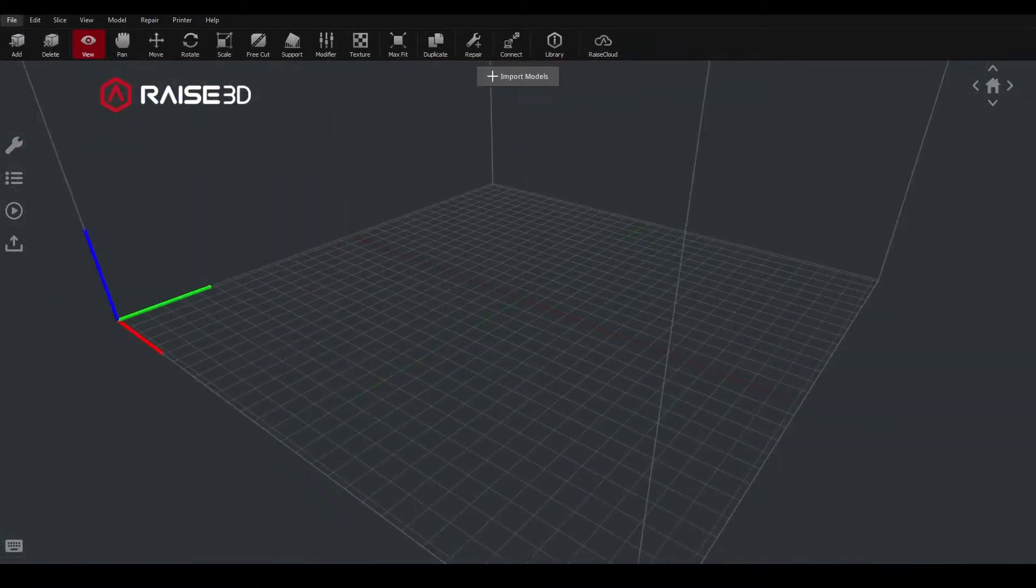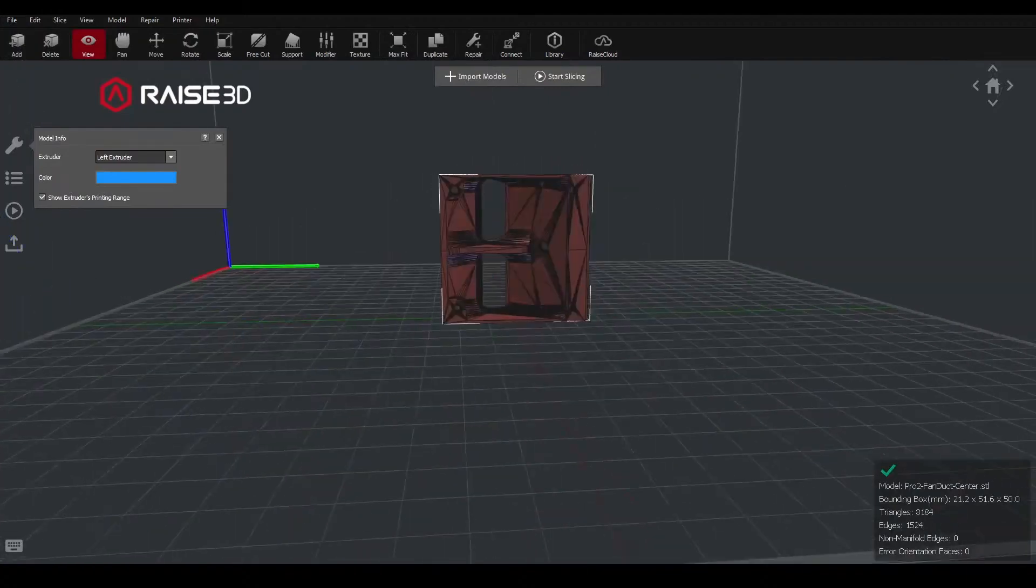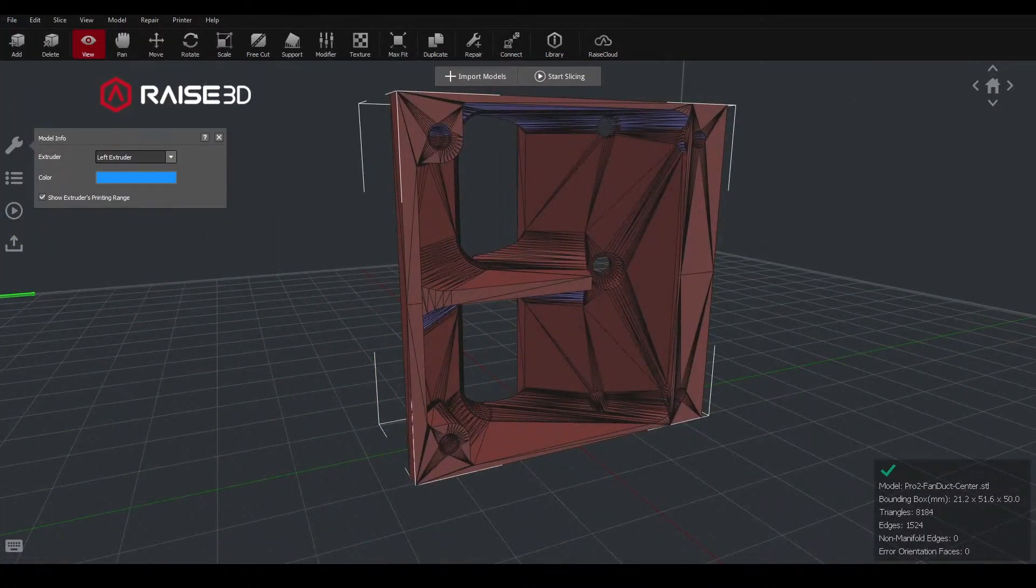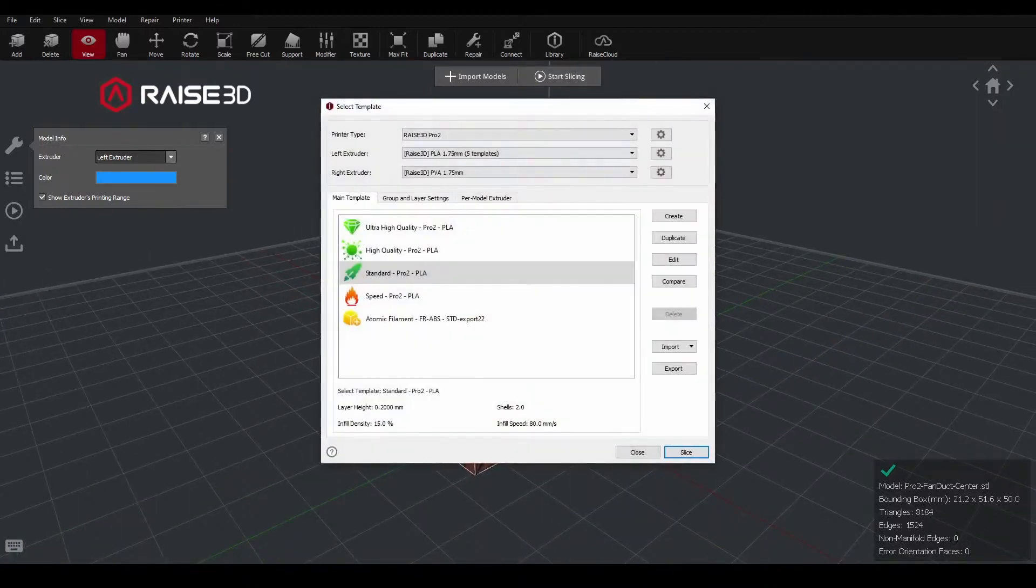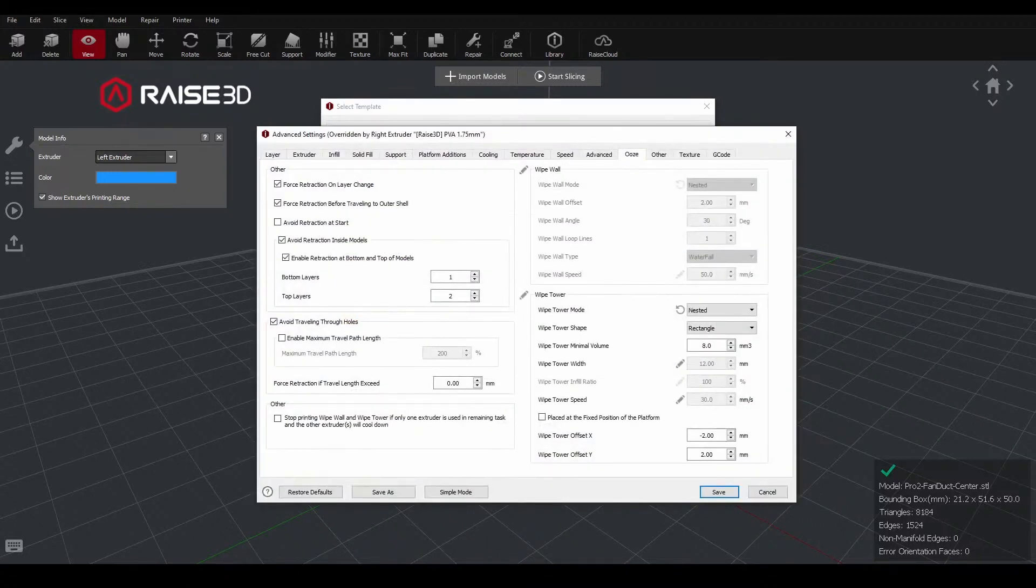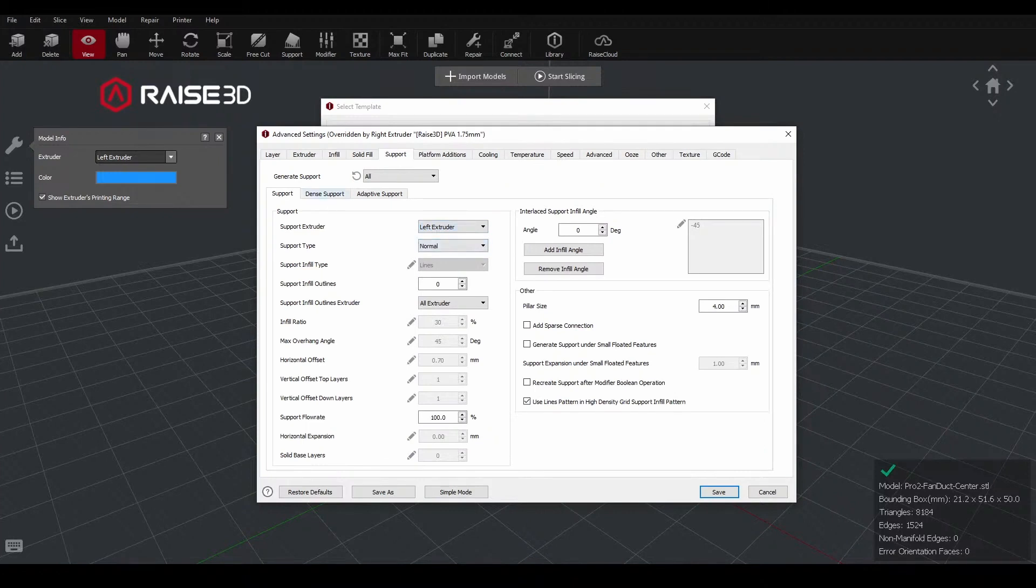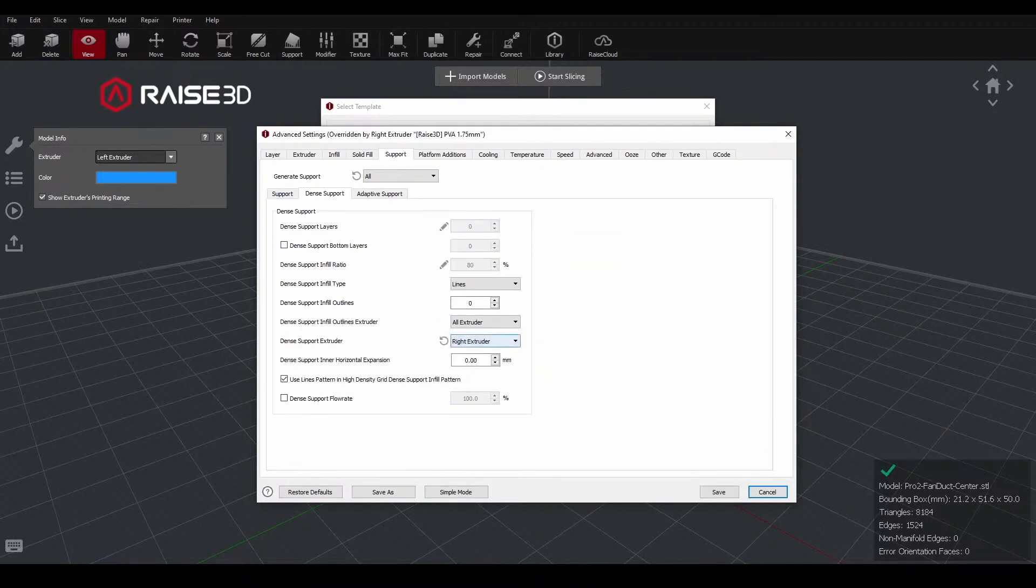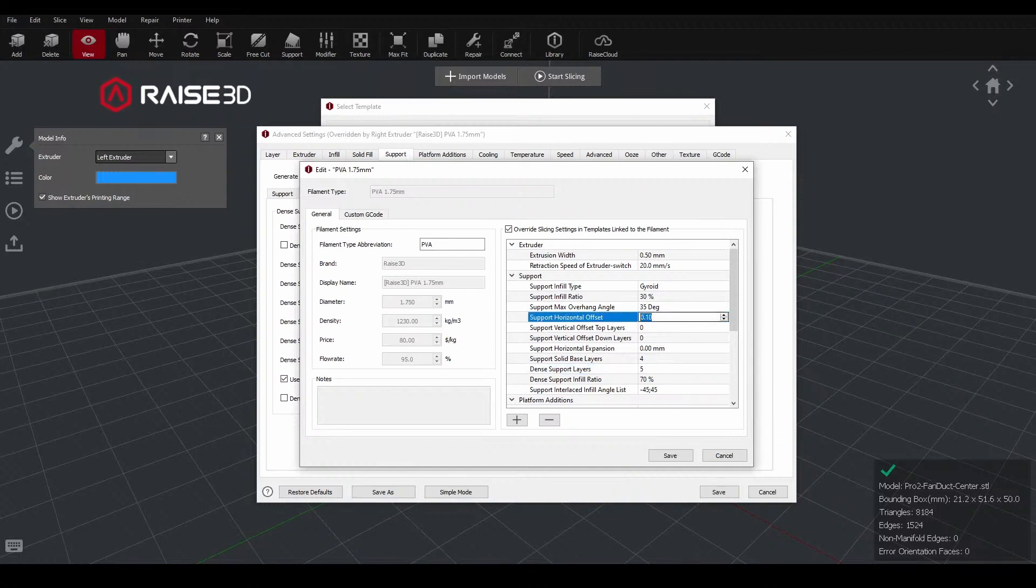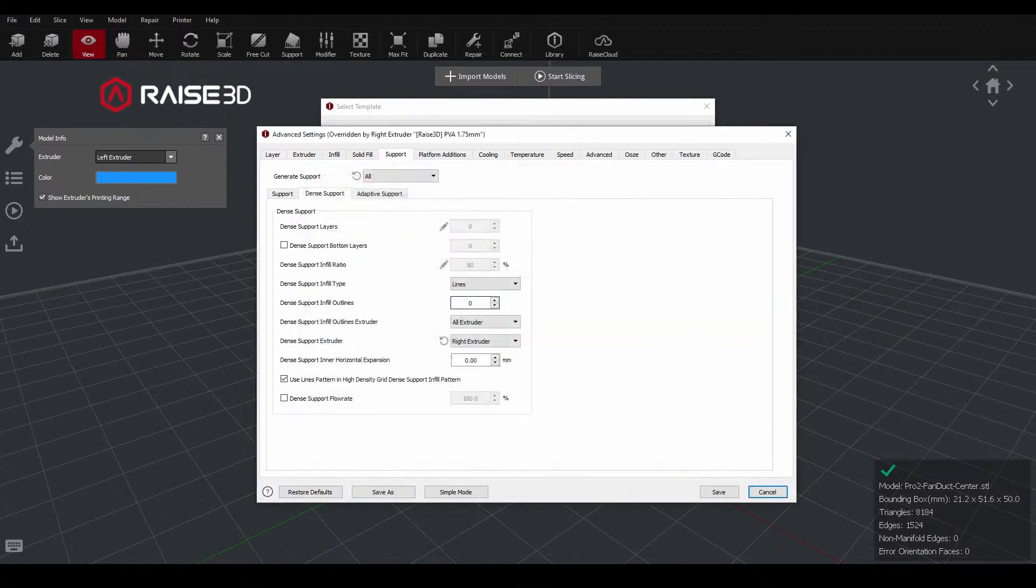Moving in to interface layers. So if we want to have just those upper and lower sections where those dense supports are going to be touching, have those set to PVA, then we'll keep our same settings for the PVA material and mostly the same settings within the template itself. Under the support tab, I want to change the main support extruder back to the left extruder. So we'll use PLA for most of those supports and then just keep the dense supports only set to the right extruder. If you do want to have more distance and more control over the gaps within the parts, I can increase the amount of dense support layers. That just pulls the PLA further away from the part so I have more to dissolve away. And then another thing that's going to be important is that you want to increase the support horizontal offset just a little bit. So that way we don't have PLA bonding along the sides, which can happen when we're bringing them a little bit closer in. So I will typically step that up to 0.3 or 0.4, depending, and then just go with the dense supports set to the right for those interface layers.